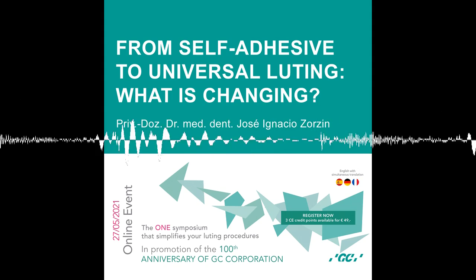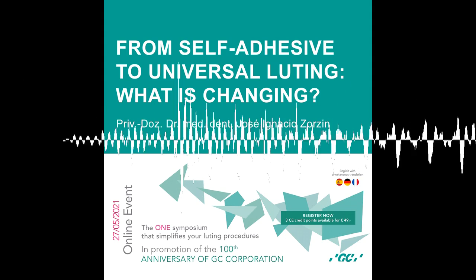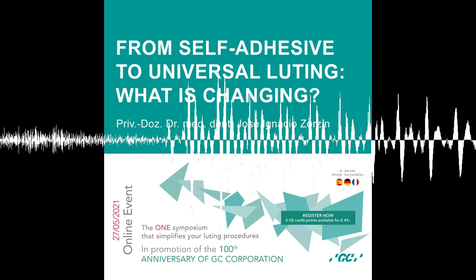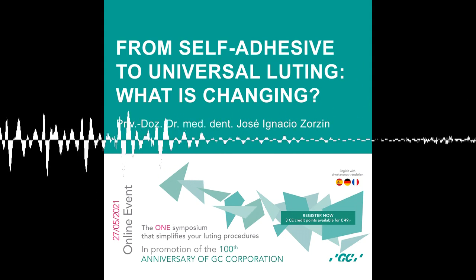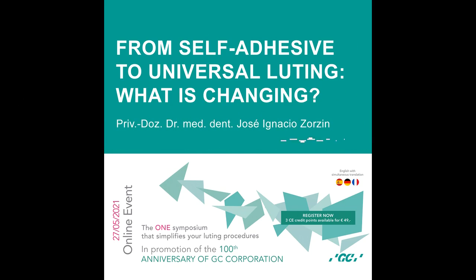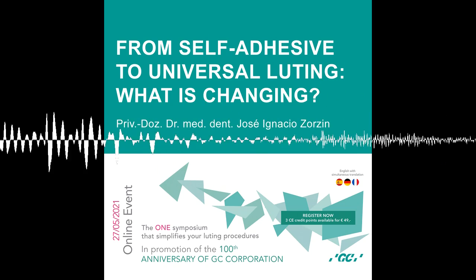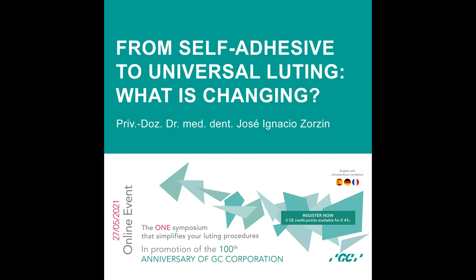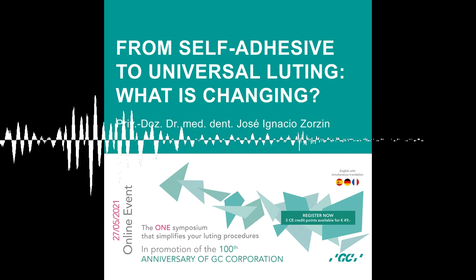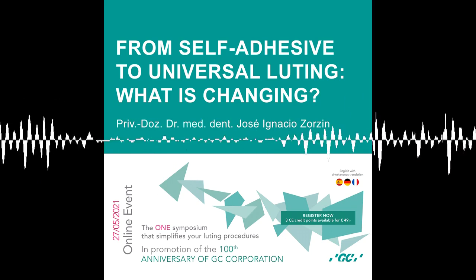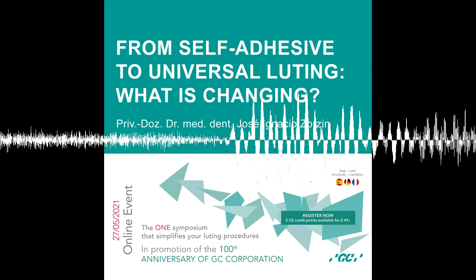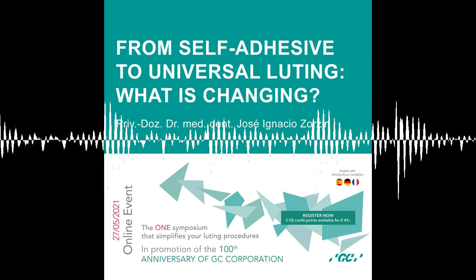I think the most important thing after etching is also to do a proper rinsing, eliminating as far as possible any remnants. Of course, this won't have the same effect as doing an ultrasonication, as when we prepare specimens for the SEM after etching ceramics, we put them inside the ultrasonic bath. But I think clinically it works if you just go for the rinsing. But this is again a decision which everybody has to take by himself. I don't want to be dogmatic on that.